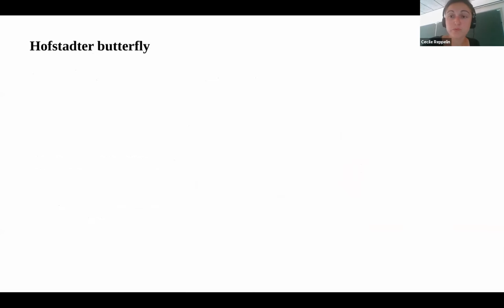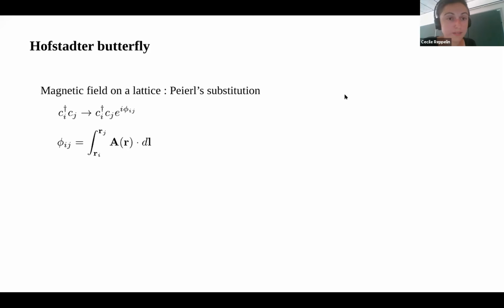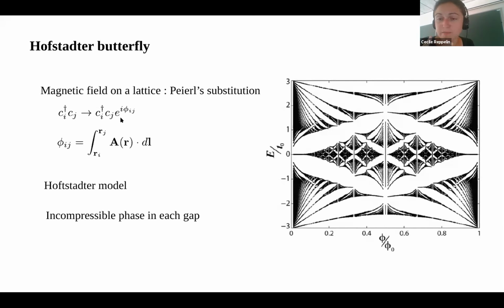So exploring all those possibilities means that you're exploring the Hofstadter butterfly that probably you know or have heard about. Basically, the idea is that when you have a magnetic field on the lattice, you can explore that with a tight-binding model by doing a Peierls substitution, meaning that you take into account the effects of the magnetic field by replacing those simple hopping terms by hopping terms times a phase. And the phase is given by the integral of the vector potential along the path taken for the hopping. This is what Hofstadter realized, that you could write a model like this, and you can write it down in any lattice. The simplest is the square lattice, but you can do a triangular or honeycomb and so on.